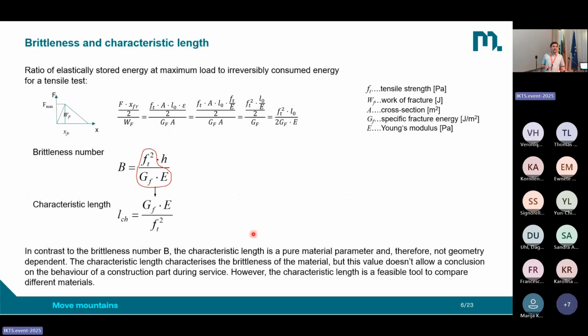If we go a little bit more into detail now, we have again this simple load-displacement diagram from a tensile test. We start at 0, we increase the displacement, we reach the maximum force, and in this example, we have a stable fracture with a linear softening behavior of our material. If we now do these calculations, so that we make a relation between the elastic energy and the work of fracture, then we can start like this. We have the force multiplied by the displacement at maximum force, and we divide it by 2, because the area of this triangle here is the elastic energy at the moment of the fracture. And this we divide by the work of fracture.